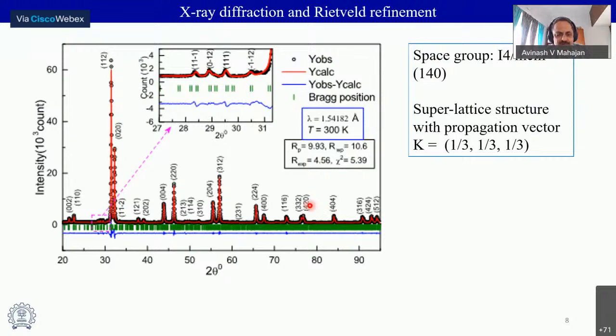Okay, so here is just a quick snapshot of the X-ray diffraction pattern. It turns out finally the structure is tetragonal because these various metal oxygen octahedra, in order to match them and keep them in the structure, tend to rotate and tilt and so forth. So the symmetry is disturbed. It goes away from the cubic and then settles in a tetragonal symmetry. So one can index all the peaks in the X-ray diffraction pattern based on that. But in addition, in the small angle region shown here, just below 30° 2 theta, one has some additional peaks, and it turns out you can index them based on a 1/3, 1/3, 1/3 superlattice propagation vector.